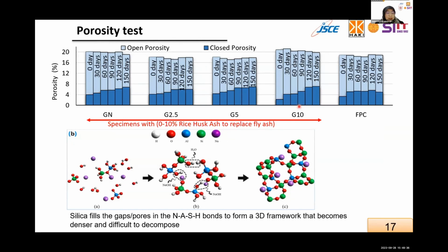And interestingly, it is evident that with the addition of soluble silicate, we replace 2.5% of fly ash, or 5%, or even 10%. The maximum is 10% replacement of fly ash. The soluble silica at the specific dosage enhances the closed porosity within the geopolymer system. This dark blue means the closed porosity. Therefore, it inhibits the ingress of chemical attack into the matrix, and it increases the density and makes it difficult to decompose.